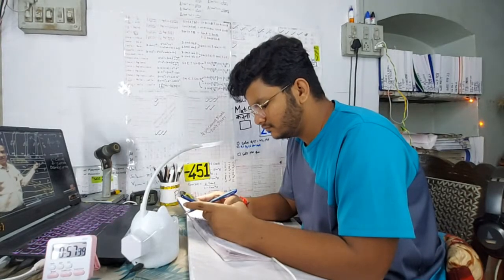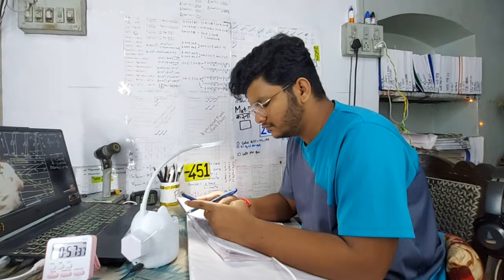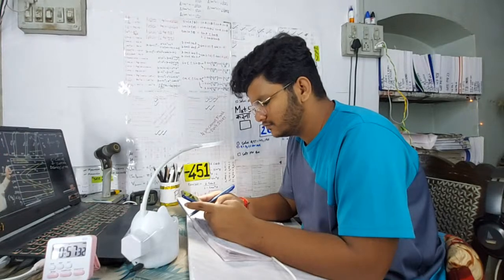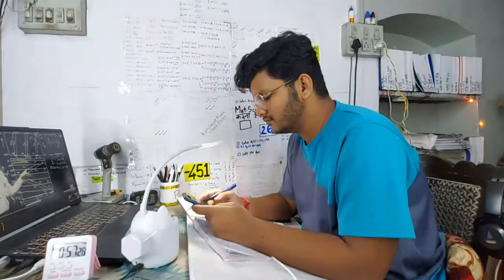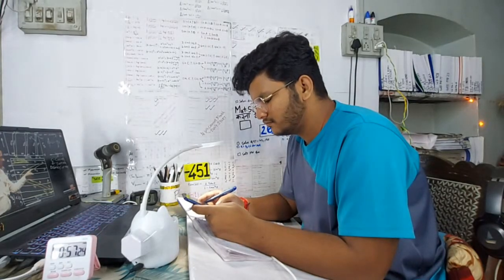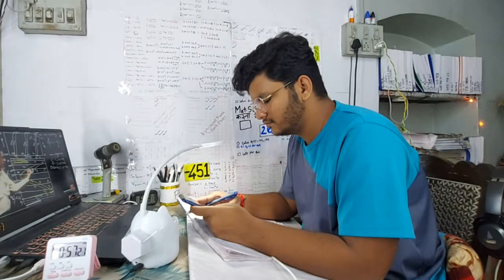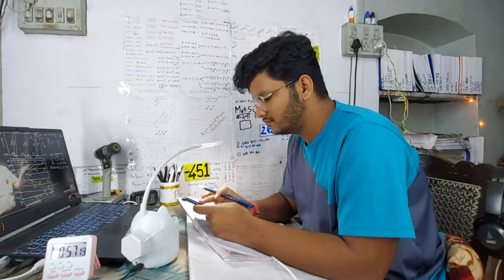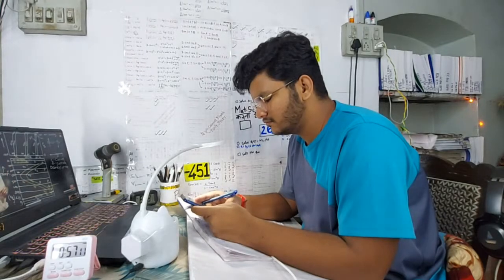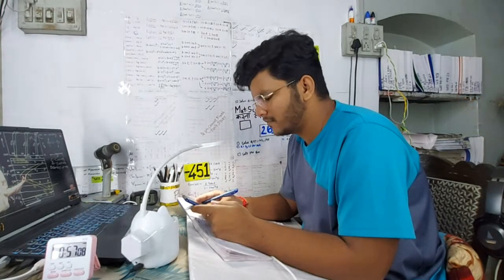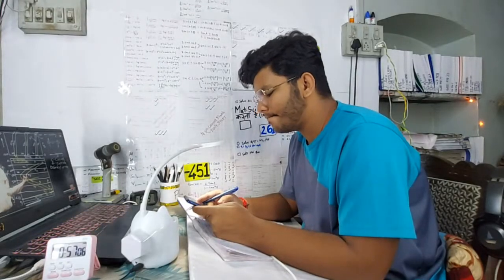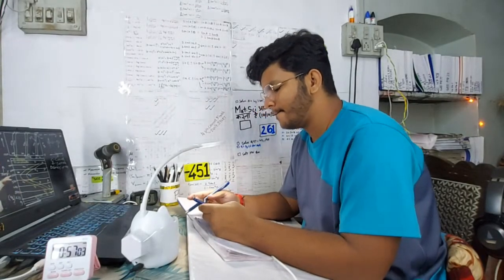So what does B1 E1 give you? B1 E1 gives you the total time taken for 100% transformation of austenite into perlite at a constant temperature of 700 degrees centigrade. Right? What does B2 E2 give you? B2 is beginning time of transformation. E2 is ending time of transformation at a constant temperature of 600 degrees centigrade. Therefore, if you take the projection of B2 E2 onto x-axis, तुम्हारे को मिलता है time taken for transformation of 100% of austenite into perlite at a constant temperature of 600 degrees centigrade. Similarly, B3 E3 gives you time taken for 100% transformation of austenite into perlite at a constant temperature of 550 degrees centigrade.